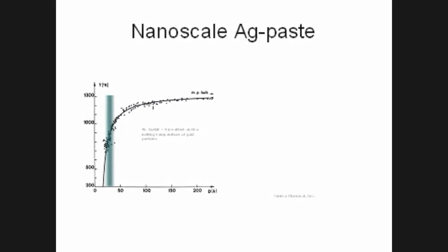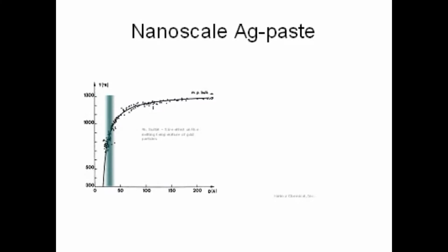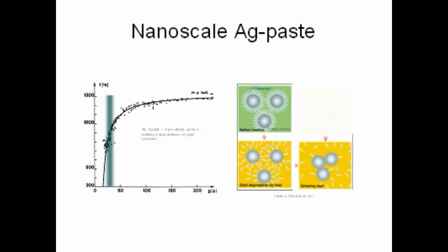One approach to overcome these challenges that I follow in my work is the use of nanoscale silver paste as a solder material. It's based on the fact that the melting point of a metal is significantly decreased when the particle size approaches the range of nanometers. In the paste, the particles are stabilized by a dispersant that has a polar acid function in the one end and a hydrocarbon chain in the other. Upon heating, the organic molecules decompose, the silver particles get in contact and the sintering is initiated.